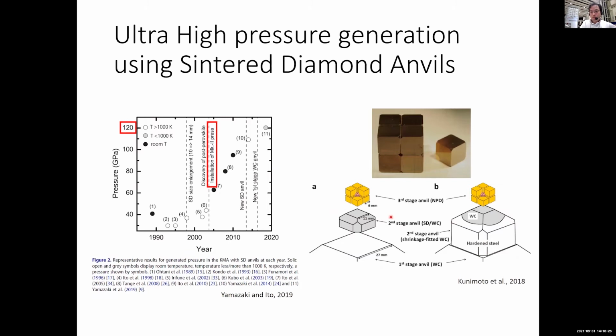For ultra high pressure generation using sintered diamond anvils, we have succeeded in generating pressure exceeding 120 GPa using commercially available sintered diamond anvils. We have also made nano-polycrystalline diamond anvils by hand and are trying to generate higher pressure using this NPD diamond. Currently, the pressure generation is only about 100 GPa due to the lack of strength of the second stage anvils, but development is progressing.